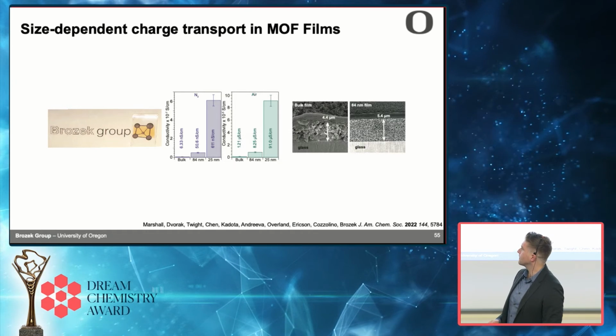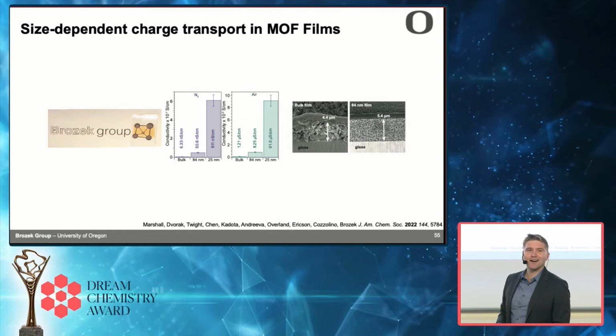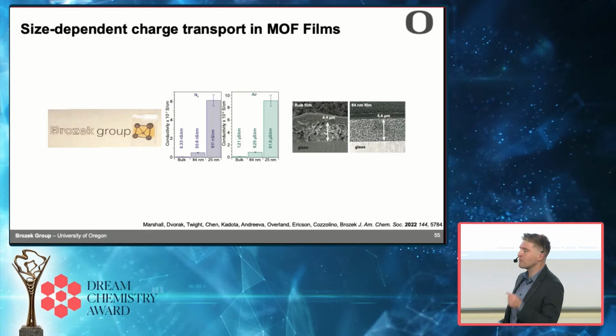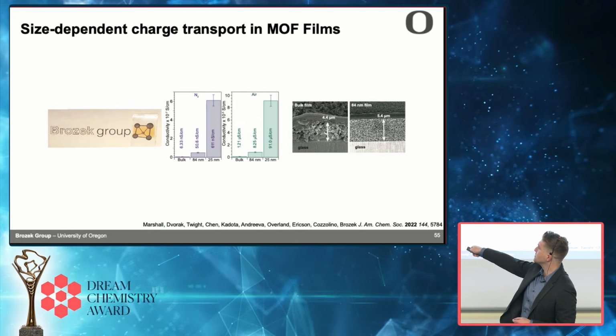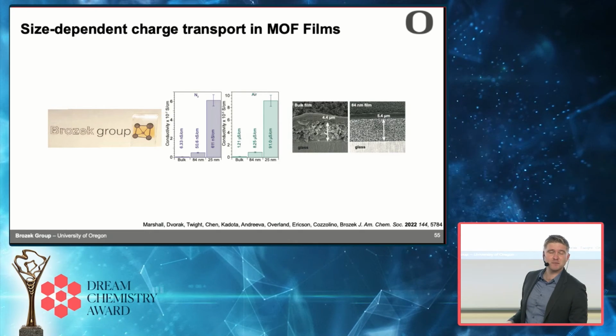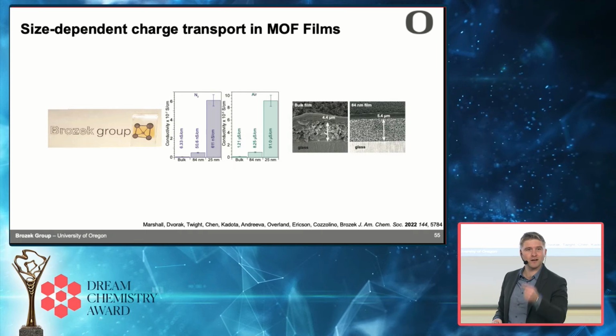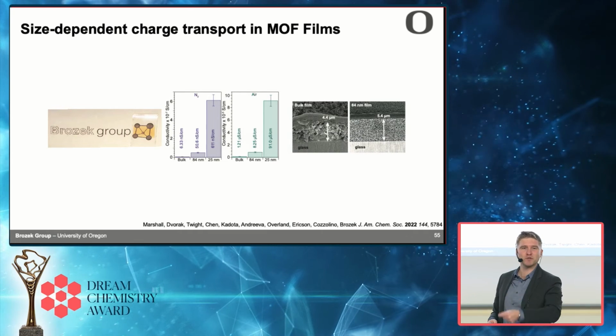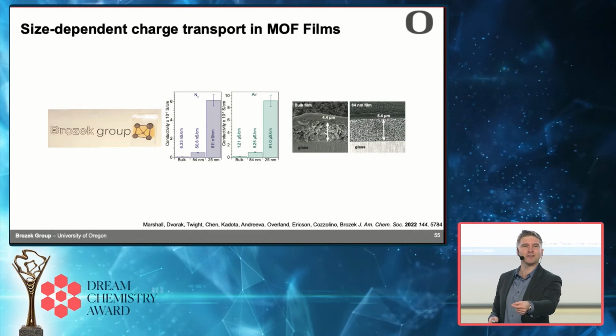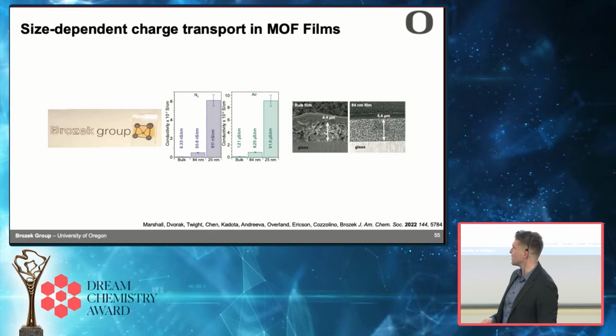But the reason lies in the fact that, as I was showing yesterday, the particle-particle contact seems to get so much better by simply making the particles smaller. And so the transport of charges between particles becomes much more effective when they're touching each other more, essentially.